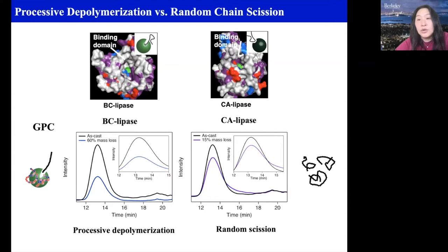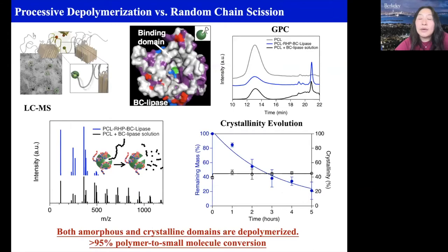So this is just a GPC graph confirming the mechanism we see. Once we have this deep pocket enzyme embedded into the plastic, it's really wonderful to see the hypothesis worked. So from the GPC, you can see that as we increase the degradation time, we don't see a reduction in the residual polymer molecular weight. This gives us the confidence that we're not doing random scission. And then you can see when we have another polymer in solution,